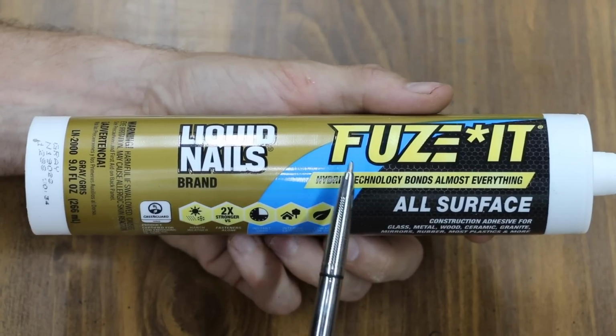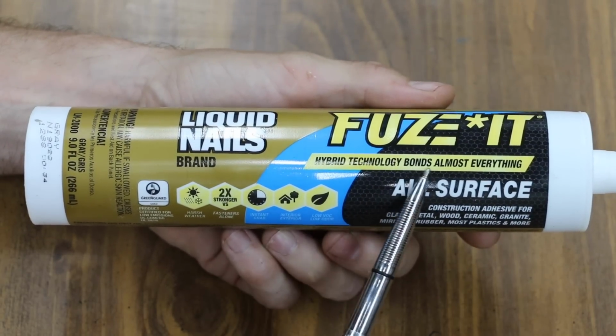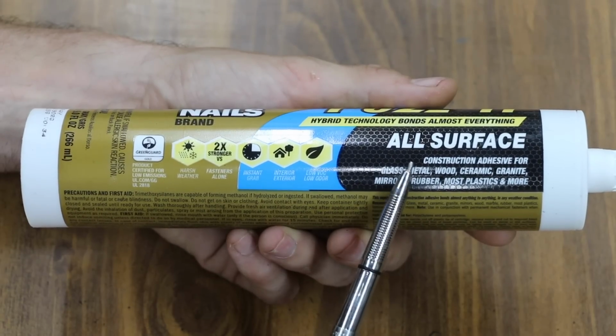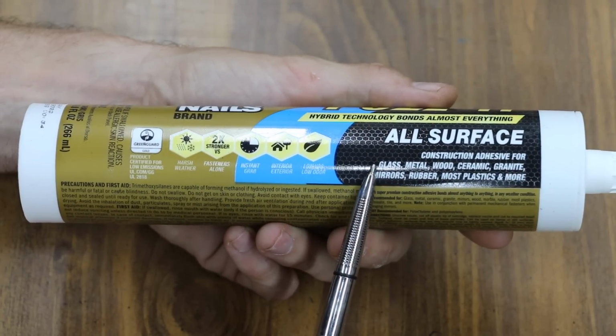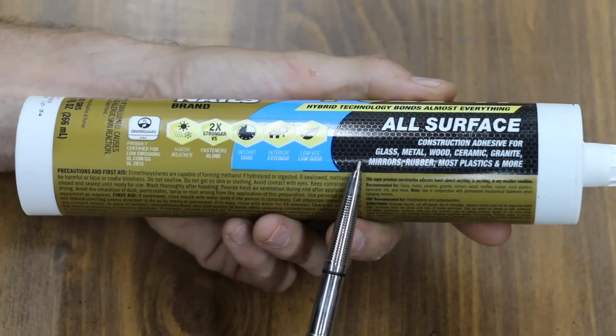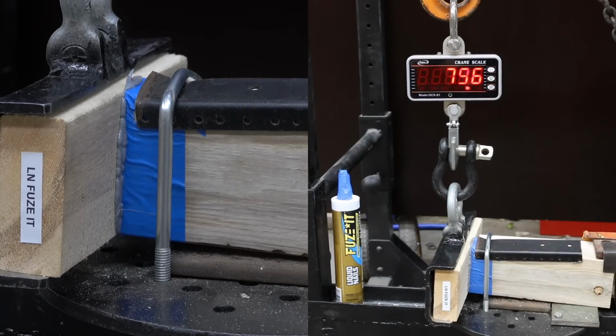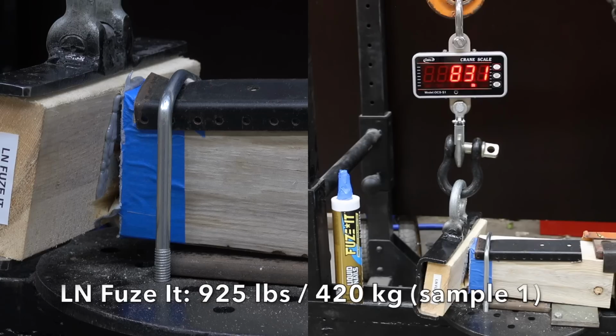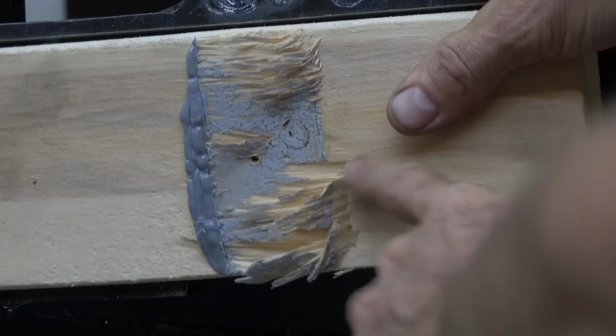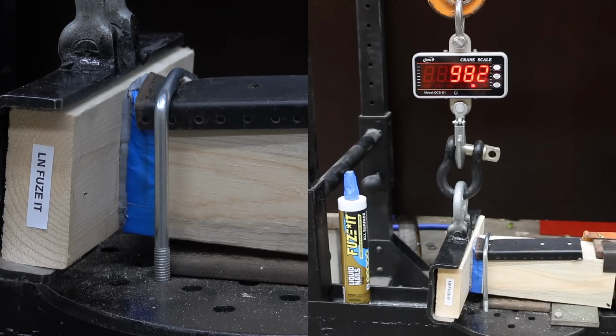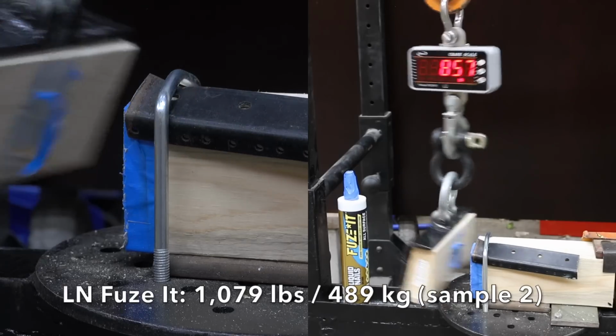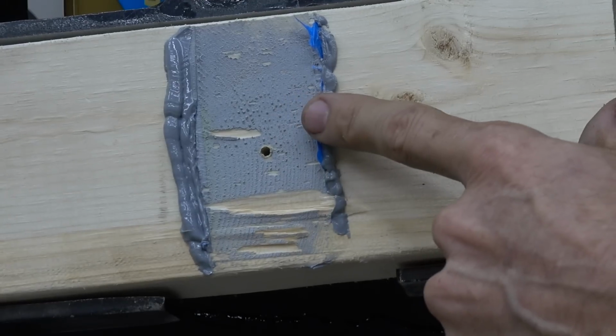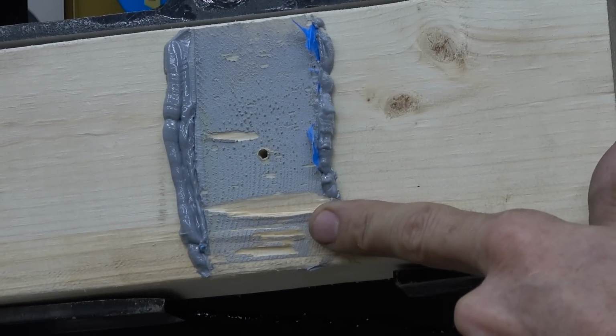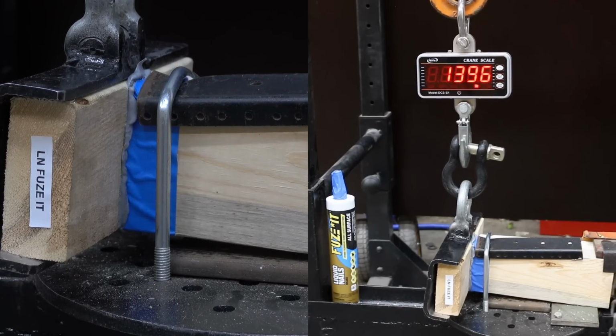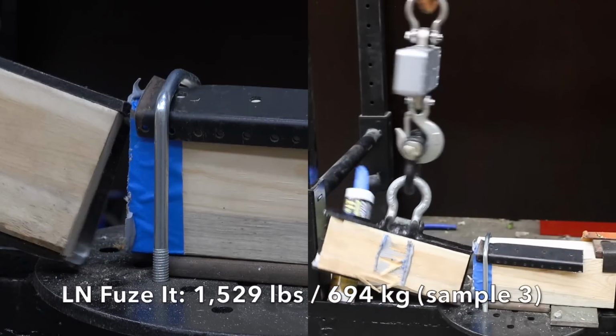We'll also be testing the Liquid Nails Fuse It. It uses a hybrid technology that bonds to almost everything. When they say all surface, they're talking about a construction adhesive for glass, metal, wood, ceramic, granite, mirrors, rubber, and most plastics and more. Liquid Nails Fuse It produced 925 pounds on the first sample. Looks like the wood partially failed on the Liquid Nails Fuse It. The next one was up a little to 1,079. For the most part, the glue let go. There was a little bit of board failure towards the bottom of the board. The third sample was up again to 1,529.